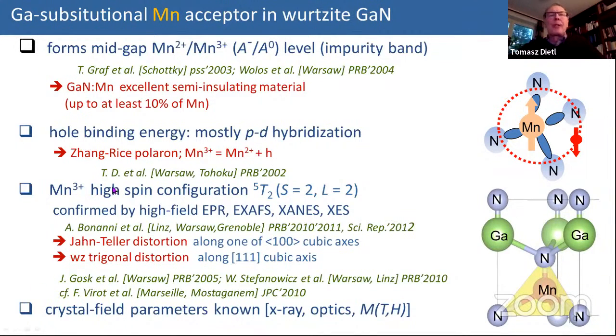And as far as physics is concerned, some of you who have a background in high-TC superconductors may know that in the case of deep acceptors, it's copper in the case of oxygen, in the case of superconductors. Here we have manganese 2+, which attracts holes, and the holes are very strongly bound, and this is Zhang-Rice polaron physics similar to high-TC superconductors. Also, altogether with this hole, there is manganese 3+, because actually we replace gallium, which is trivalent, by manganese, so manganese is 3+ in gallium nitride.